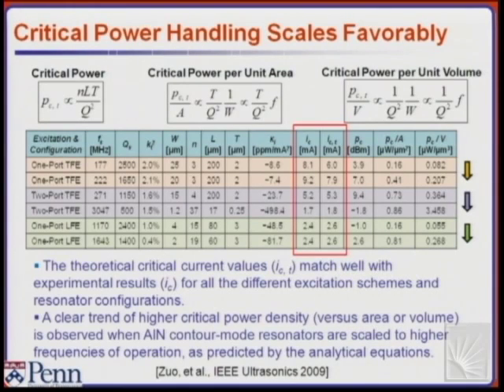And actually we derived a scaling law for this critical power that per unit area scales as the thickness of the film, inversely proportional to the Q squared and the frequency. So the higher the frequency, the higher the critical power that you can put in your device. It's true that you're losing a little bit in thickness, because to go to higher frequency we really need to make them a little thinner. But the frequency is an advantage.